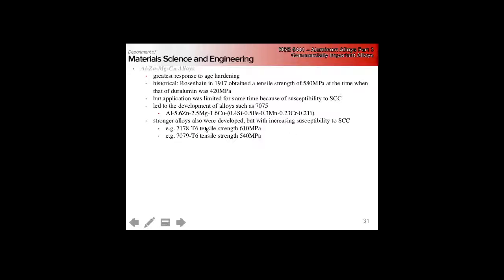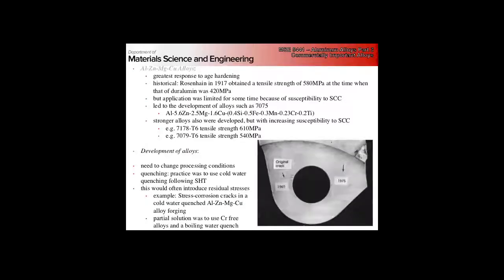We can make, at the same time, people were working towards even stronger alloys. We get up to 610 MPa in the T6 condition for 7178, but the trade-off is we make our corrosion properties even worse. It's always the trade-off.